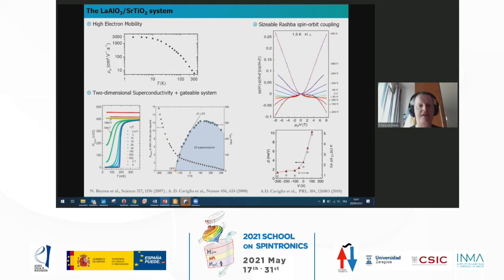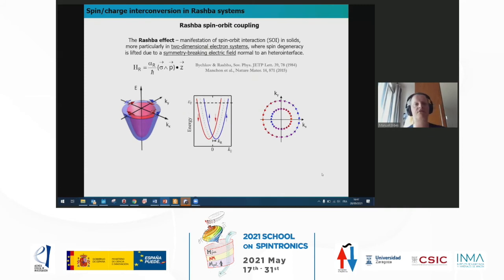And then through fittings, these authors were able to extract the Rashba coefficient, which is here alpha. It's on the order of a few tens of milli-eV angstrom if you want to compare with other systems. It's not very, very large, but it can do a lot of things, as I will show you, and it depends strongly on the gate voltage. So what is Rashba spin-orbit coupling?